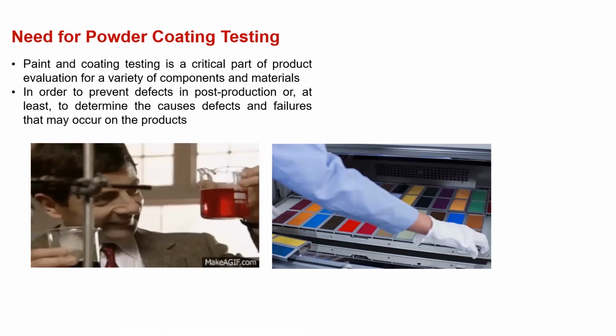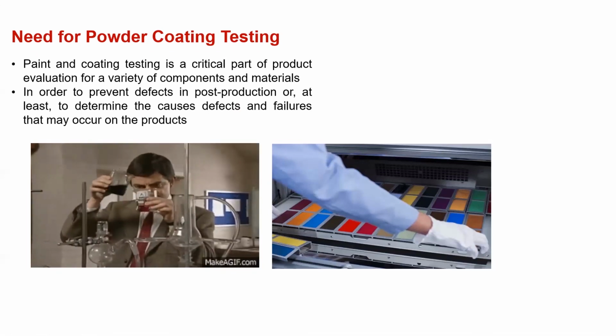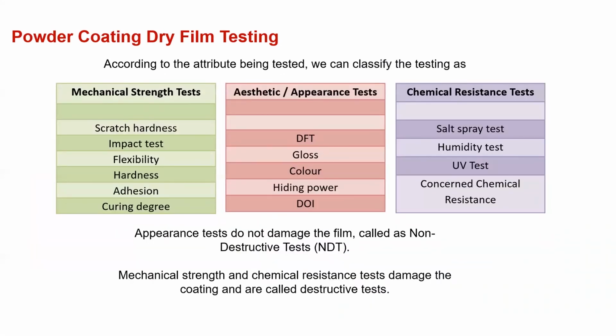So basically, powder coating testing is a critical part of product evaluation. So naturally, you need to do it on a regular basis. There are three different types of tests. What we call mechanical strength tests, which include scratch hardness, impact, flexibility, hardness, adhesion, and curing degree. So this is mainly what we are doing at the application end. Aesthetic appearance tests: DFT, gloss, color, hiding, DOI, in which DFT and gloss normally we are checking here, and color sometimes, if you are doubtful. Chemical resistance or corrosion resistance: salt spray, humidity, ultraviolet test, chemical resistance test. Now, these appearance tests usually do not damage the coating. So we call it NDT, non-destructive, and the rest are usually the destructive tests.